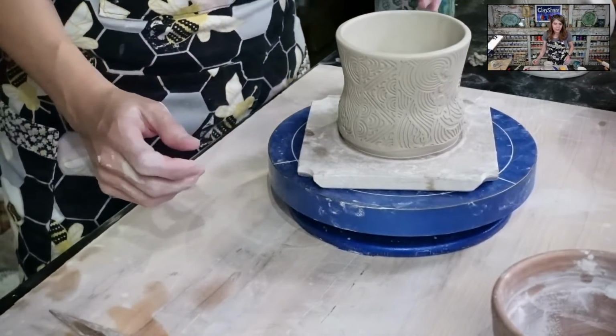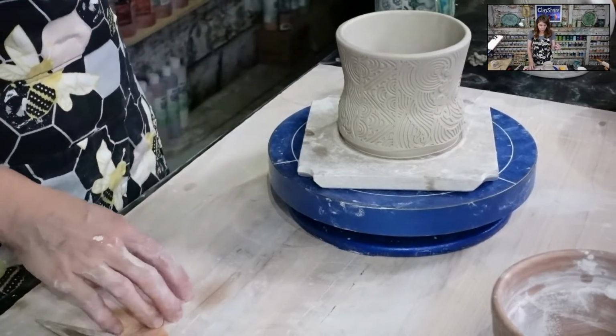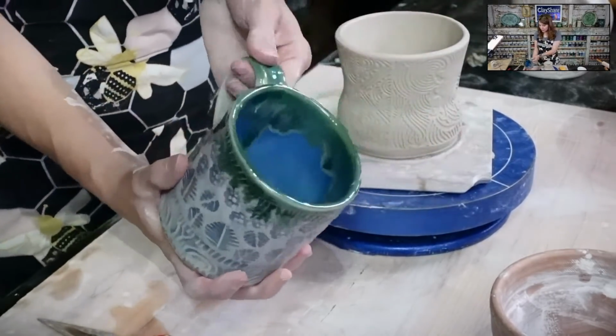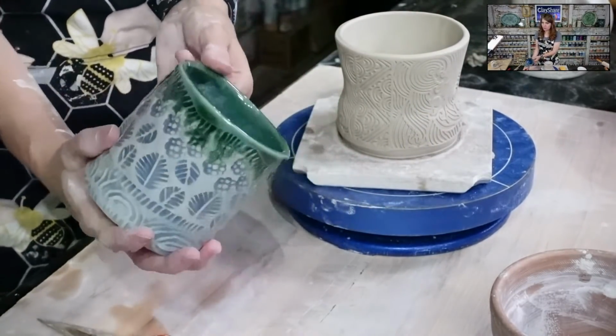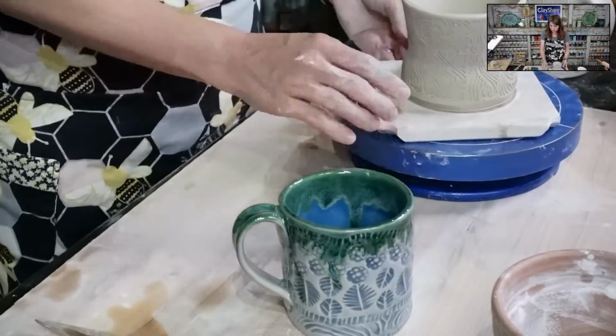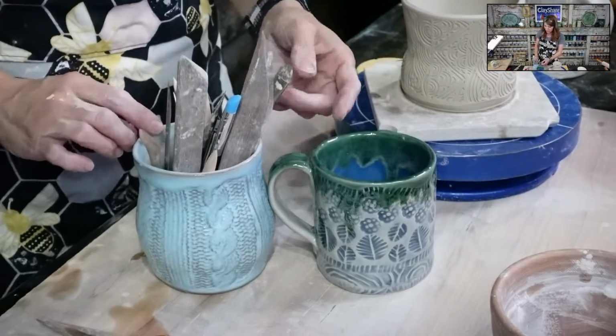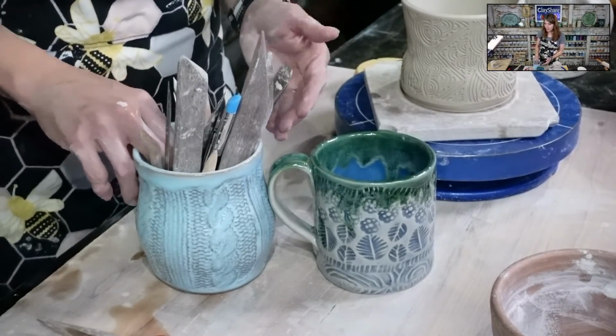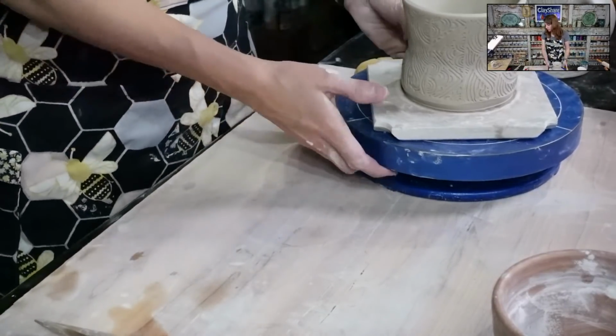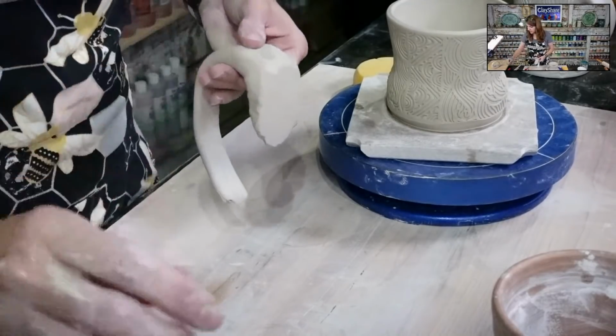So you find that in the glaze firing, your handmade mugs seem to be pulled out of round by the handle. Right. So Mary Jane, what happens is when you put the handle on, sometimes the weight of the handle will actually pull the mug out of round. So what I will do is build a little support, as my handle's drying, and I'll show you, I will just stick it up against something that it can rest on so it doesn't sag on you, because that's what happens. It happened to me if I'm not paying attention. So it's really a common thing. So maybe we can talk about that a bit when we do this.